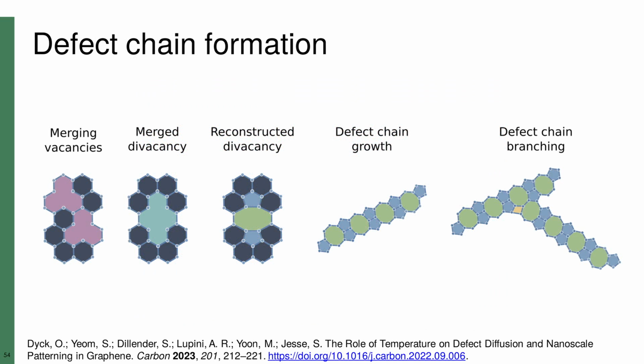But these vacancies have some probability of meeting each other, merging together, and restructuring into a reconstructed di-vacancy. This structure requires much more energy to diffuse through the graphene lattice, and at the temperatures we're working with here, they are essentially fixed in place once they form. They also create a strain field in the surrounding lattice that encourages the vacancies to diffuse to the top and bottom of this structure to relieve the compressive strain, which ultimately results in the sequential buildup of long defect chains, one vacancy at a time.